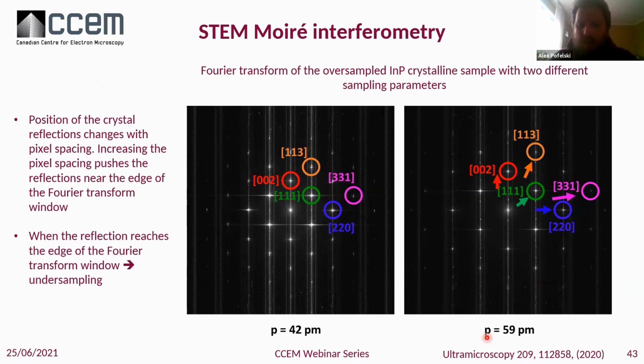The idea here is to look at how those reflections are varying with the pixel spacing. And the general rule that we can see here is that when you increase the pixel spacing, the reflections are getting pushed away and getting closer and closer to the edge of the Fourier space. And that's exactly what is happening. Until you reach the edge of the Fourier space, you are in a condition of oversampling. The moment you reach the edge of the Fourier space, you become undersampled.